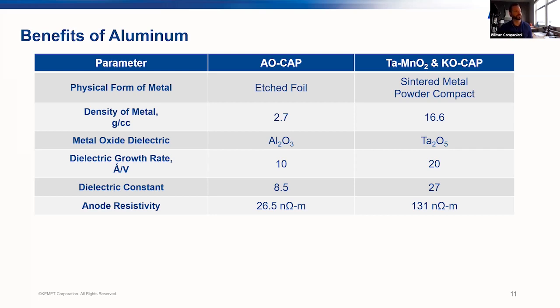But one of the things to note that's a really positive for aluminum polymer is the very low resistivity of the anode material. So the very low resistivity of aluminum, it's about what is that, maybe 5 times less than that of tantalum. So these very, very low levels of ESR that you can get from aluminum, that's in part due to that very low resistivity of aluminum.